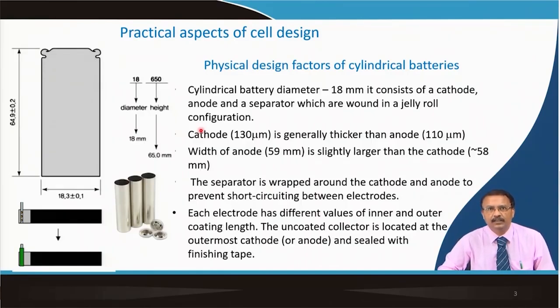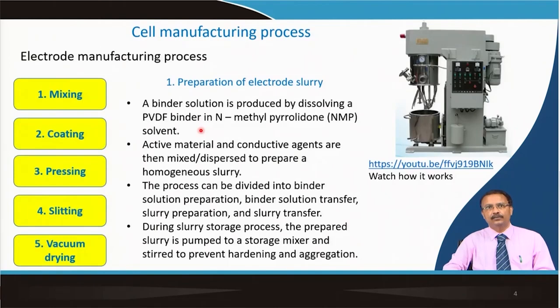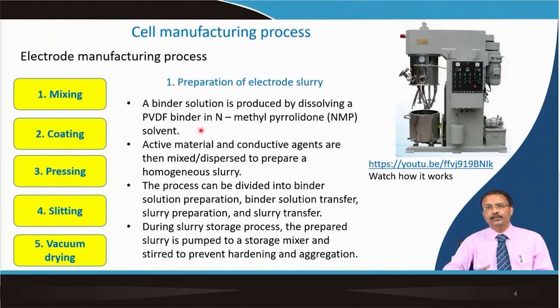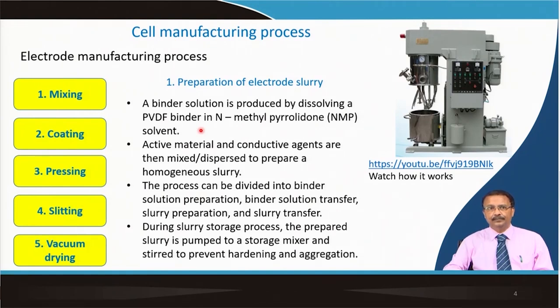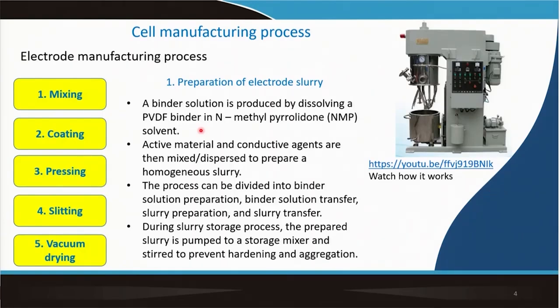Now you can understand the physical design factors for making cylindrical cells. The cell manufacturing process starts with electrode manufacturing, which constitutes several steps: first, mixing the active material with binder and conducting agent to form a slurry; then coating, mostly by tape casting; then roll pressing to increase tap density and ensure the electrode is properly adhered on the current collector; then slitting to the exact length and width for winding; and after slitting, vacuum drying so there is no trace of water absorbed during fabrication.